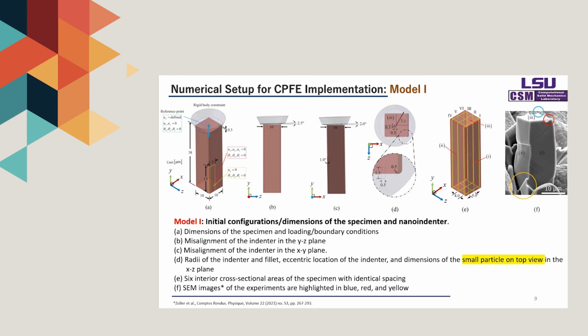Now we have the numerical setup for the crystal plasticity finite element implementation. The figure shows the initial configuration of the micropillar sample. In this configuration, we try to apply the real-life conditions of the experimental setup sample, such as geometrical imperfections, misalignments, as you can see here, and eccentric location of the nanoindentation, as shown in the SEM image. This is depicted in the SEM as you see here: localized debris.